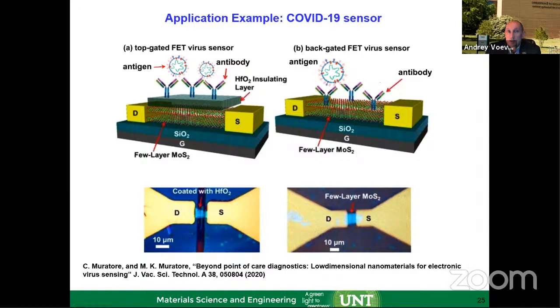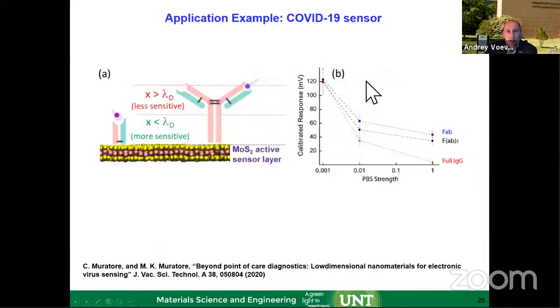And it happened; the sensitivity of this approach is very high, and they were able to demonstrate this in making a device. They also found that instead of using the entire antigen, like in all this assembly shown in here, it is better to use a fragmented one, so you can bring the charge transfer from that COVID-19 virus group somewhere in here, so that the shorter the pathway, the easier, and the higher the sensitivity will be. And they demonstrated that this can have very good parts per billion sensitivities, and here you see that you can get signals in the millivolts as a response.